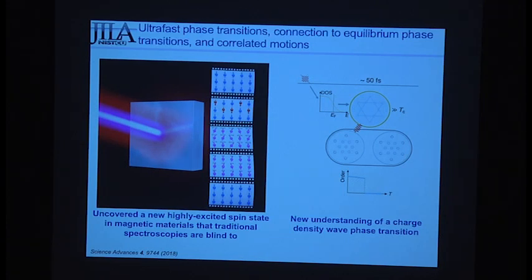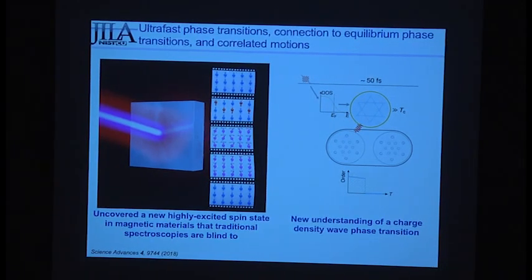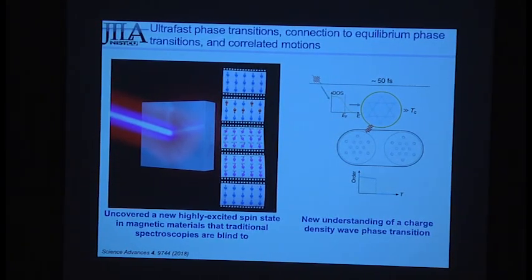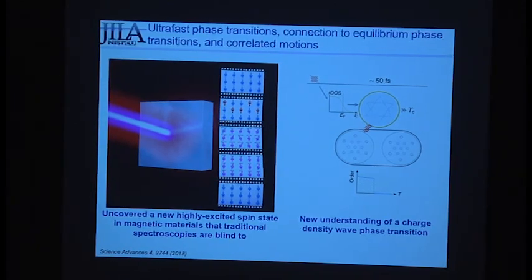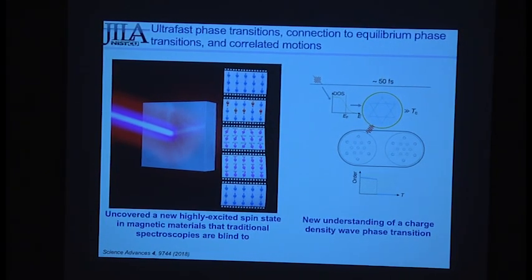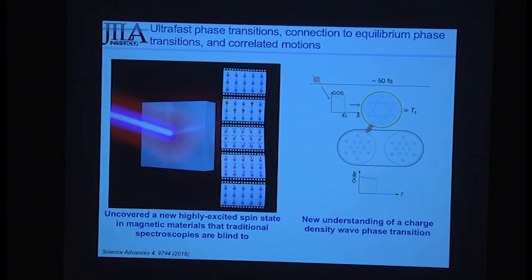The surprise there is that when you drive a fast insulator to metal phase transition, you couple only to certain phonons, and maybe that's not too surprising because in some of these materials there is a very strong electron-phonon coupling. The surprise was that the other phonons took more than 100 picoseconds to actually come to that same temperature. So the actual pathways were not what we anticipated.